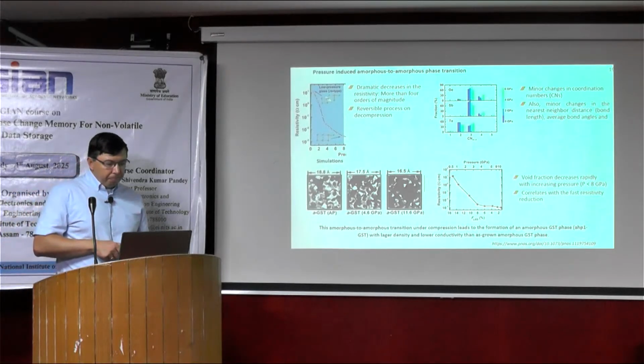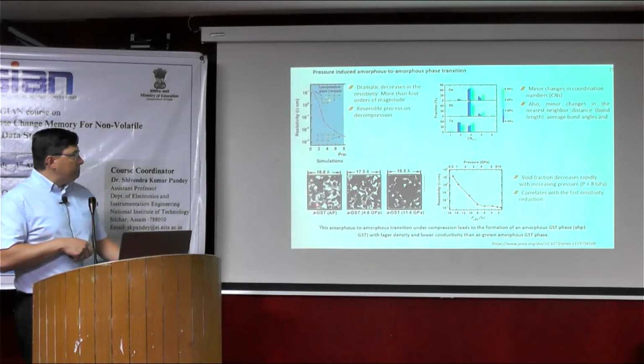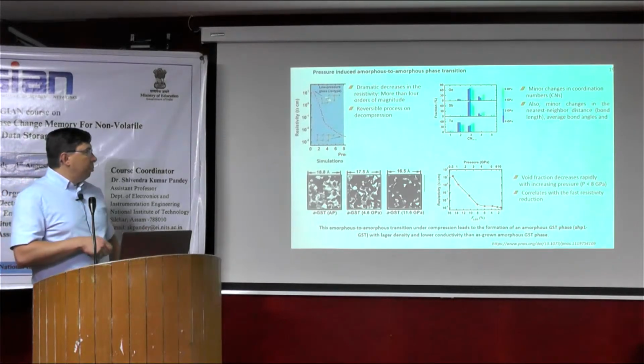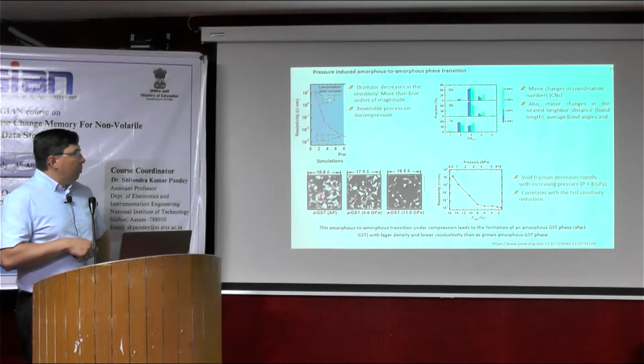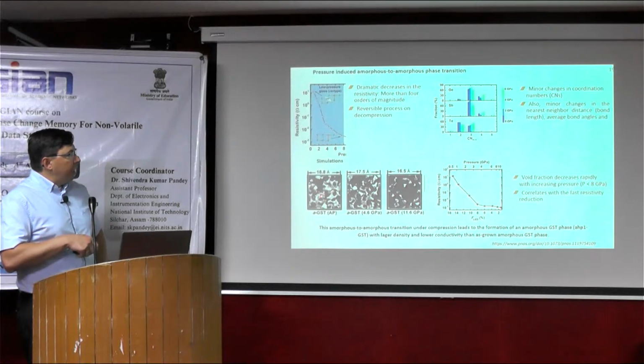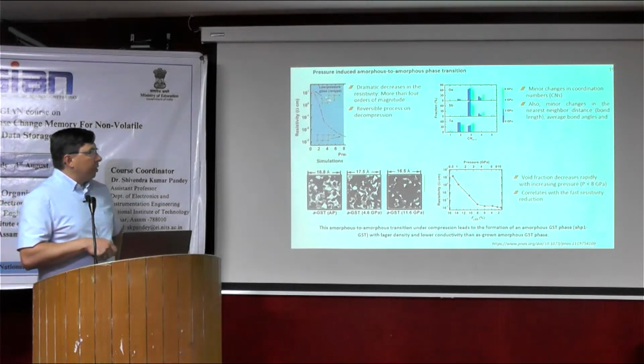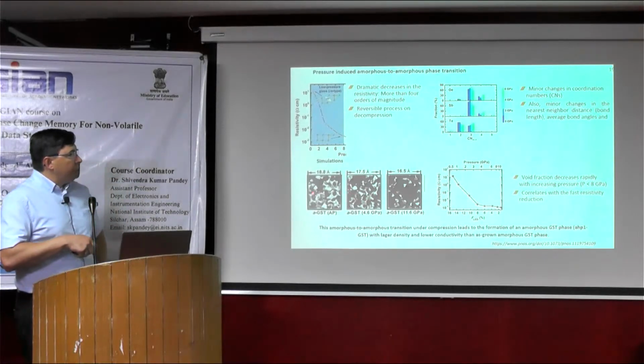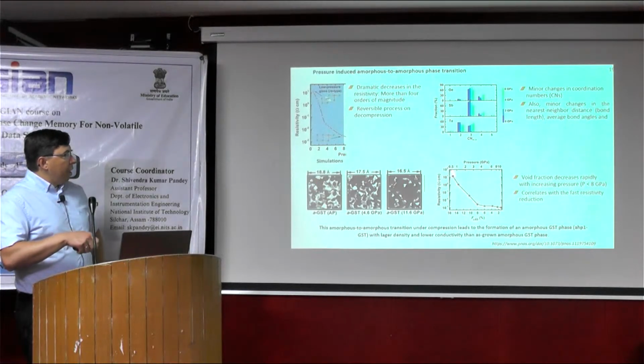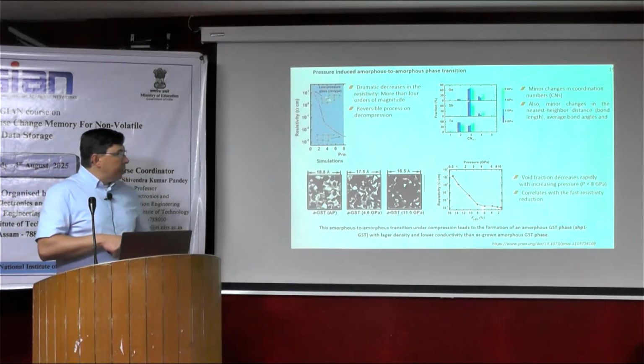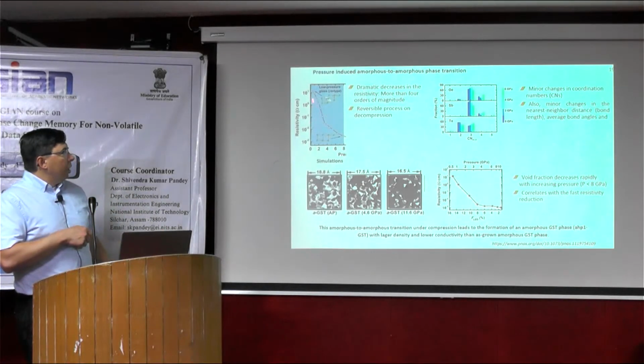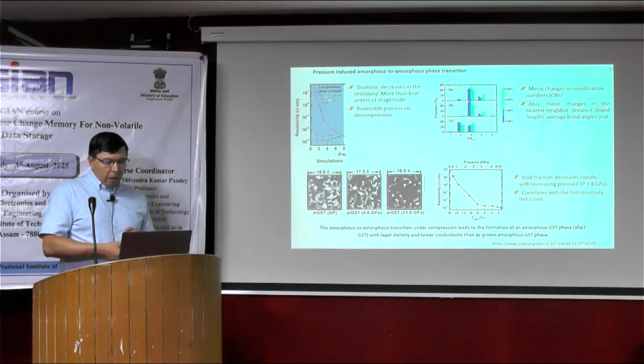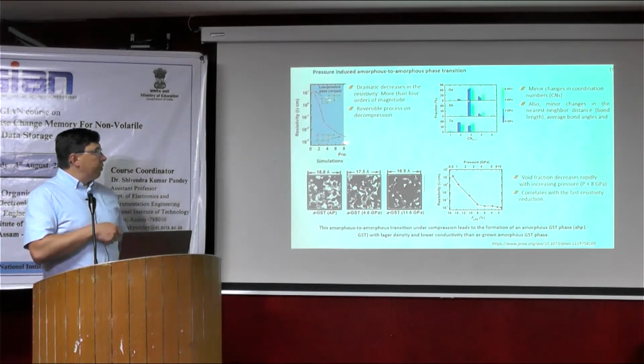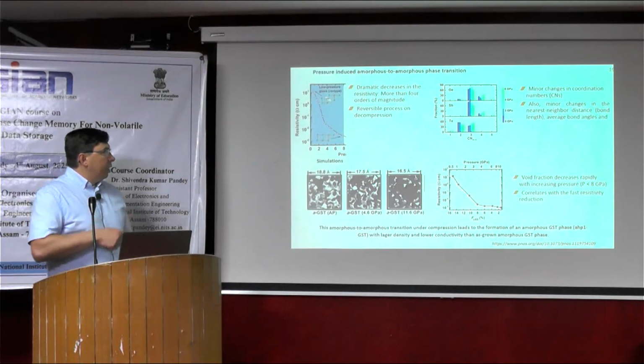But what happens here, the simulations showed that if we compress the material, then the number of voids existing in this phase starts to rapidly decrease. So the fraction of voids you see here, if it goes from this state to this, the number decreases. It can also be quantified. So in this case, we have a transition from a less dense to a more dense phase under compression, and this more dense phase has different properties from the less dense phase.